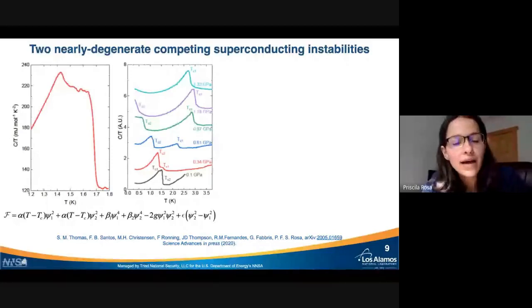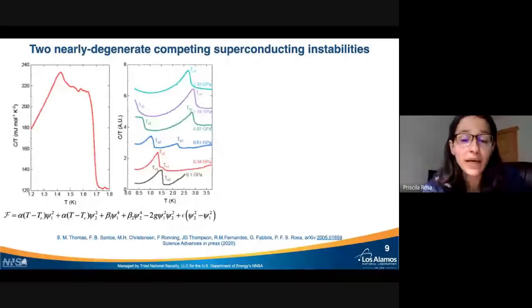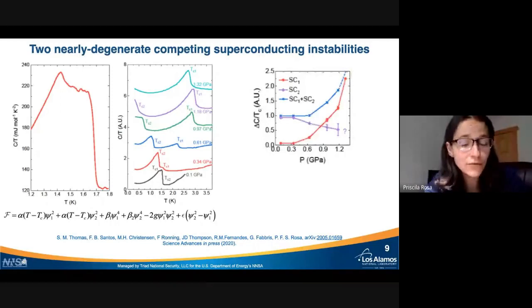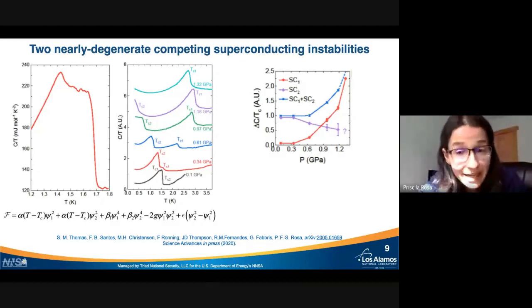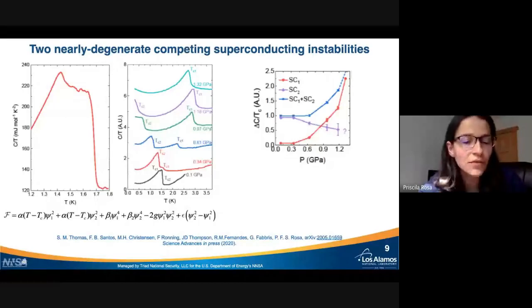So two complex order parameters, psi1 and psi2, and we can see what happens under applied pressure, because that's a really clarifying tuning parameter that we can use. And we see that under pressure, the sum of the heat capacity peaks that we can actually measure should be constant as a function of pressure, and it is. At low pressures, it's constant, so it is consistent with this phenomenological competition.